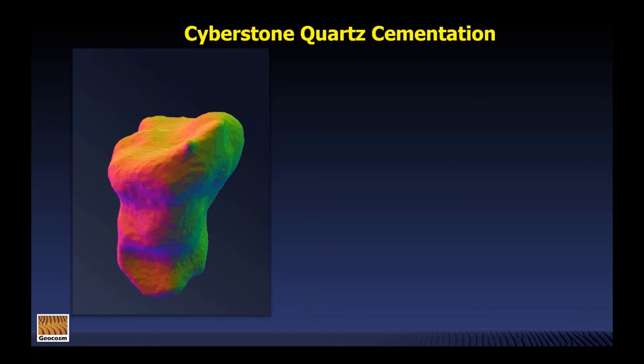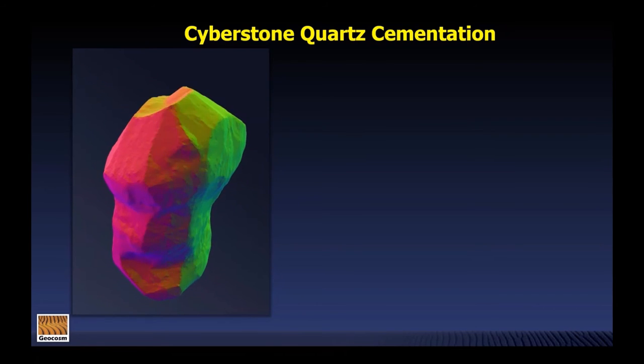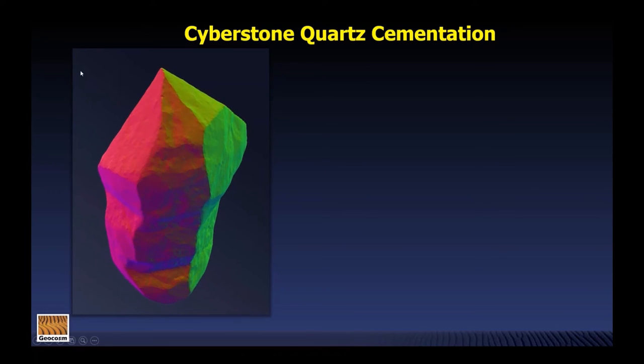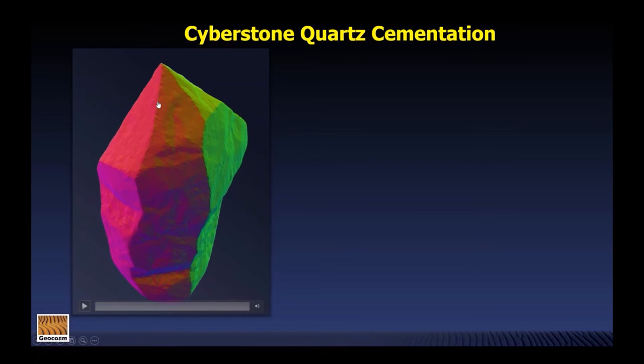So what we're going to look at here is a micro CT scan of a natural sand grain, and we're going to grow a quartz overgrowth on it. I think you can see the pyramidal faces forming on this quartz overgrowth, as well as these prismatic faces. And one of the things that we wanted to strive for was the ability to simulate a quartz overgrowth on any irregular sort of shape.